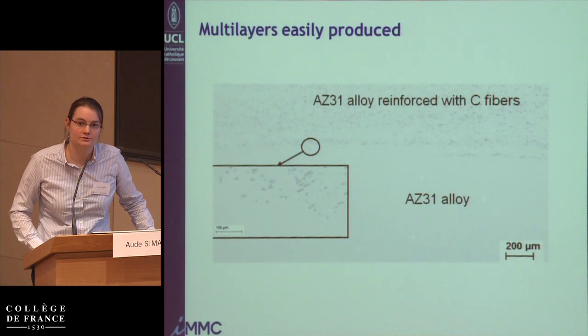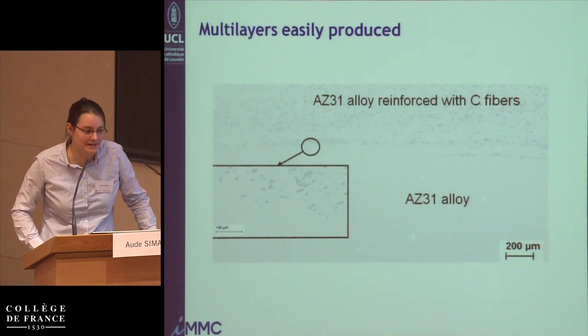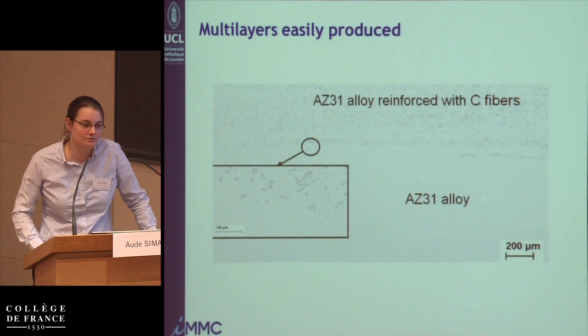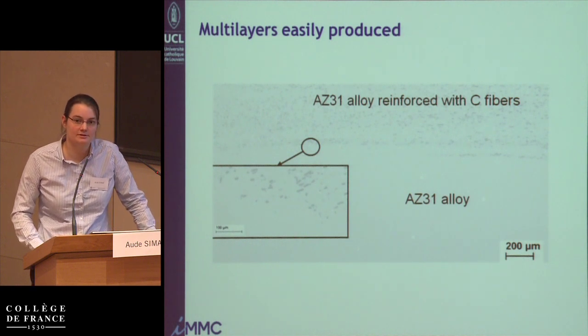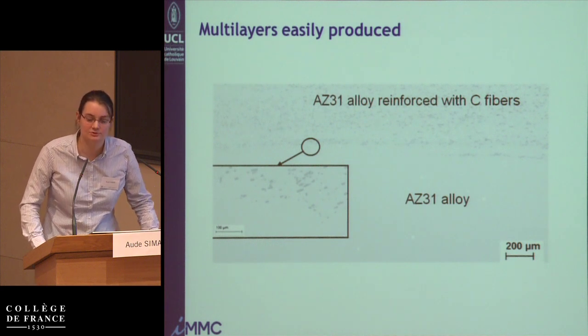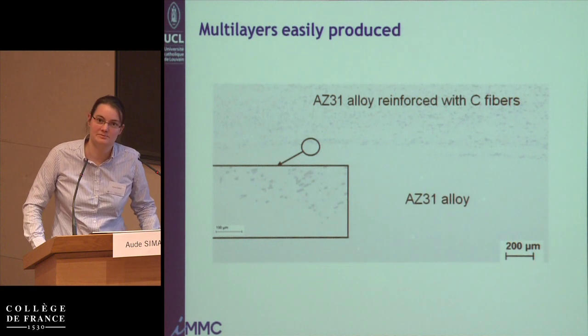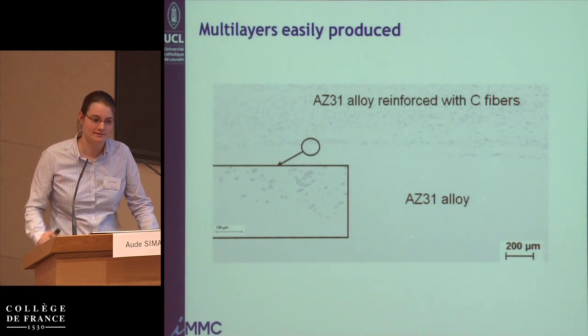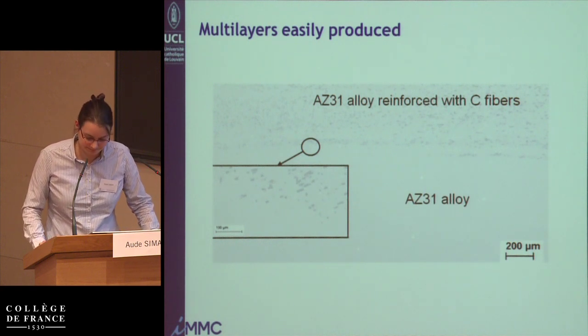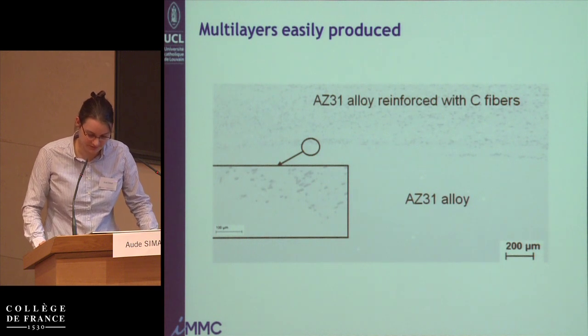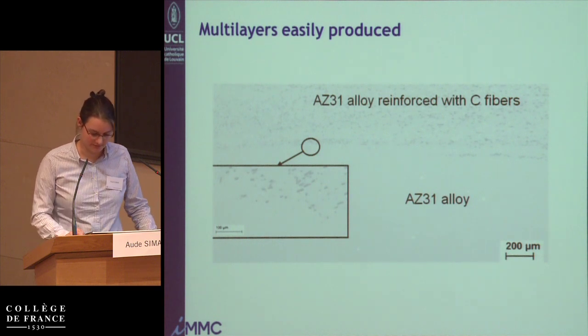And also for the carbon magnesium system, the problem is galvanic corrosion, and so you don't want to have your carbon fibers to be too close to the environment, so it might be interesting to keep them inside the material, so you avoid the problem of contact with the environment.